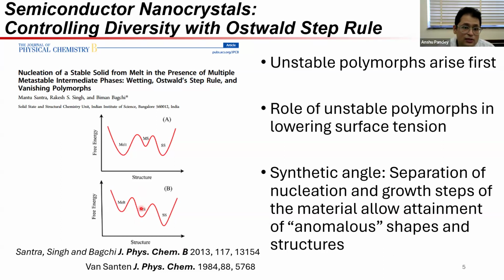Now, what this means is because there are all these local minima, and the chemistry which we use is like this wonderful interface of being partly governed by thermodynamics, partly by kinetics, we can actually intercept these phases and use them to our benefit. And that is indeed what really is the secret of colloidal chemistry, why we can allow materials to grow in very weird shapes or very weird structures, simply by being clever about which of these phases we are intercepting. Are we working out of the melt? Are we working out of the metastable phase, or are we directly trying transformations of some kind of a solid? Let me illustrate what I mean by that.